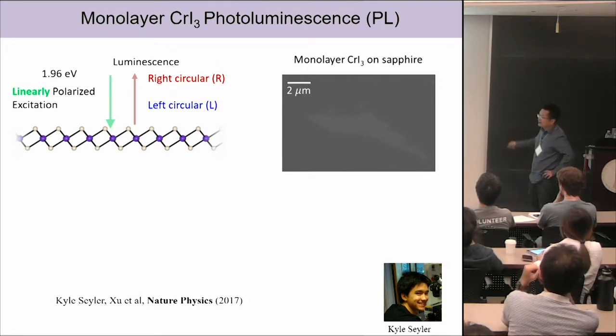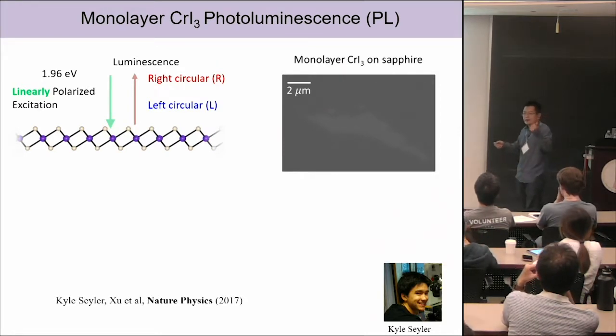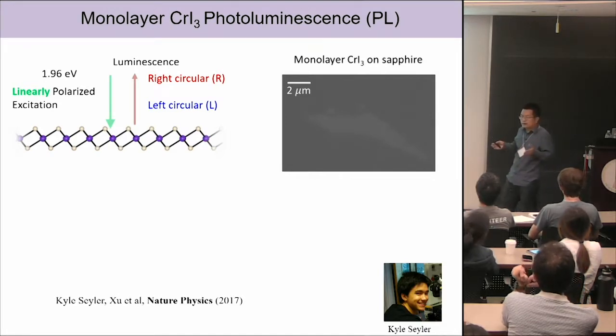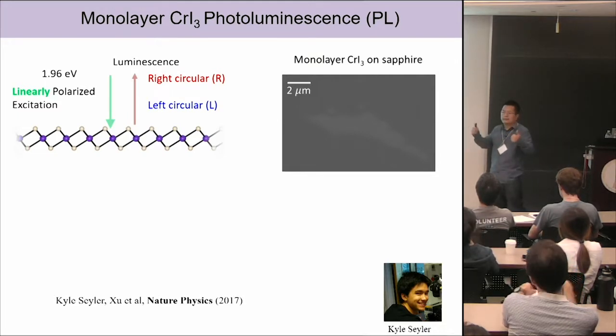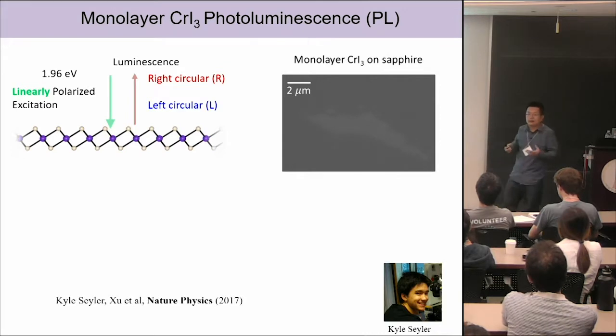So linear polarization is a superposition of sigma plus and sigma minus. It doesn't break time reversal symmetry of the system. Then we do circular polarization resolved PL measurements. If the system doesn't break time reversal symmetry, then there should be no preference for right or left circular. But if you see a spontaneous circular polarization, it means the system actually has time reversal symmetry breaking.